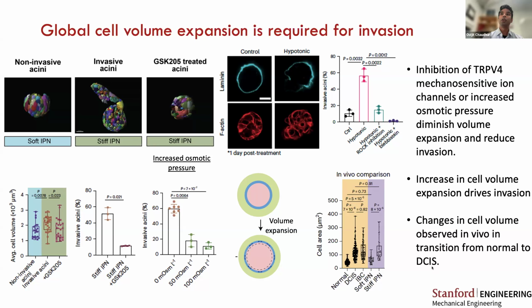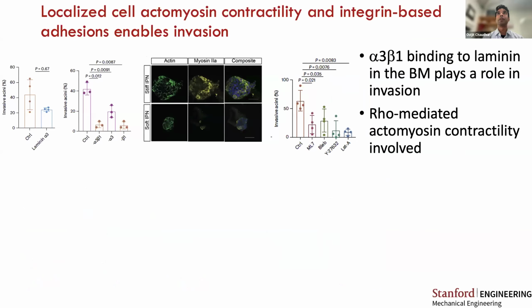But interestingly, what you'll notice is that between pre-invasive breast carcinoma and invasive breast carcinoma, the cell volume or area is similar. This suggests that the cell volume increase is necessary, but maybe not sufficient to drive invasion, and maybe there are other mechanisms involved. So along these lines, we looked at the role of actomyosin-based contractility coupled to the basement membrane through integrins. We blocked integrin binding to laminin using blocking antibodies, and that reduced invasion. And similarly, if we inhibited Rho-mediated actomyosin contractility, that also reduced invasion.